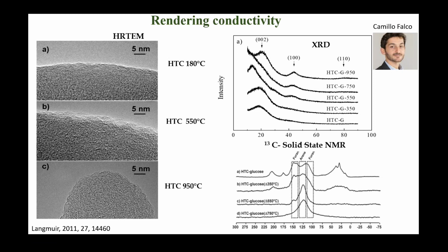And you could follow this nicely by NMR, as I showed you. The NMR of the material at low temperature shows furans and aromatics and carboxylic groups and aliphatic groups. So as you carbonize them further, you would lose all these functionalities and you turn all the furans into aromatics and you have a more classical structure of a hard carbon that now is also conductive. So you could just make them conductive by heating them up.